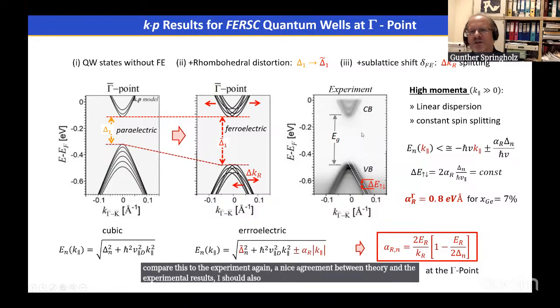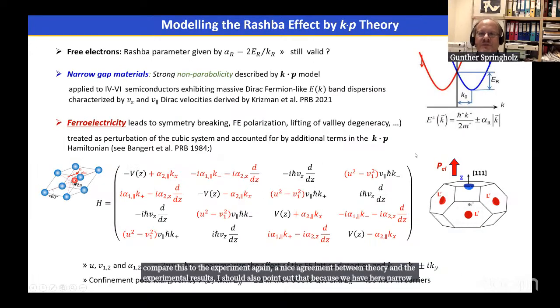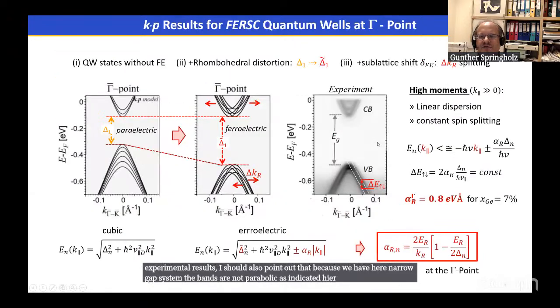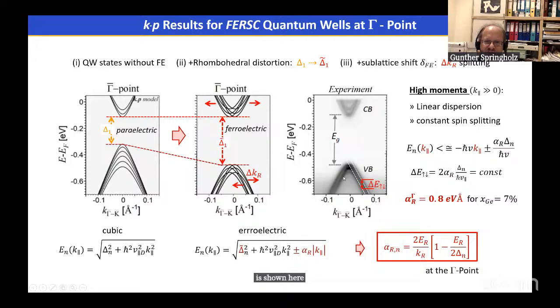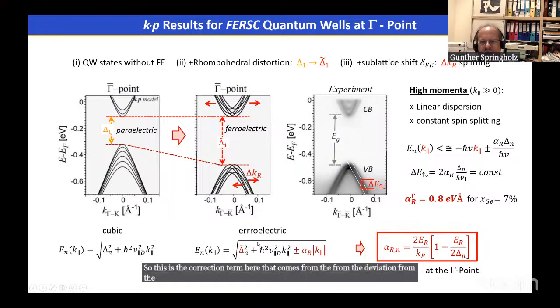I should also point out that because we have here a narrow gap system, the bands are not parabolic as indicated here, but they have a massive Dirac energy momentum dispersion, as shown here. And for that reason, the Rashba parameter is different compared to the usual derivation for a free electron system. So this is the correction term here that comes from the deviation from the parabolic band structure.